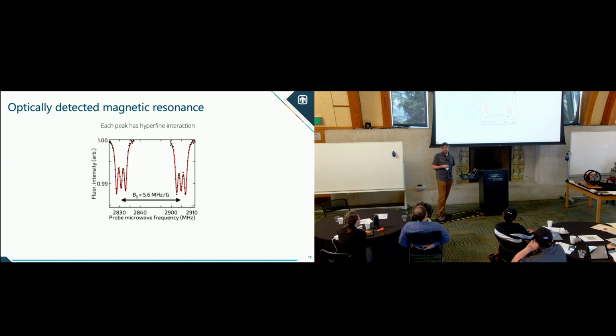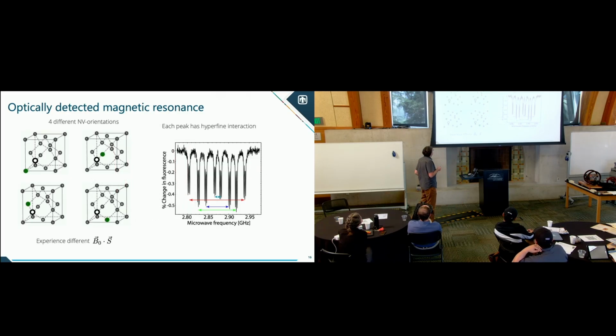All right, it's actually still a little bit more complicated too, because not only do you have one orientation of NVs. If you apply a biased magnetic field, ideally you're applying it along an axis of an NV, but you can actually have 4 different nitrogen vacancies if you have ensembles of them. So your biased magnetic field is going to be in a different orientation for each of these NVs, and at low field limit, this dipole-dipole interaction defines the quantization. Until you get past that, D is the predominant spin orientation, and then you'll get a different Zeeman splitting depending on which NVs you're looking at. So they experience a different B0·S term, right?